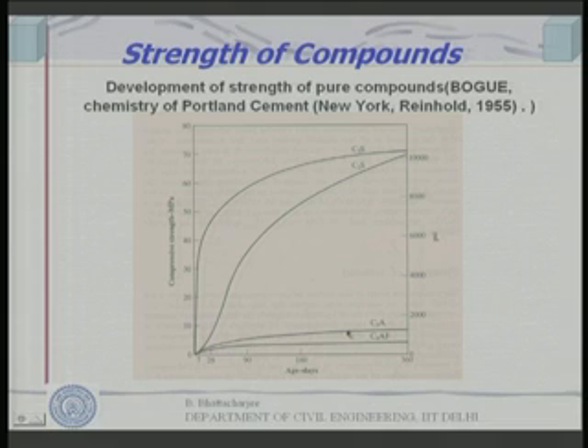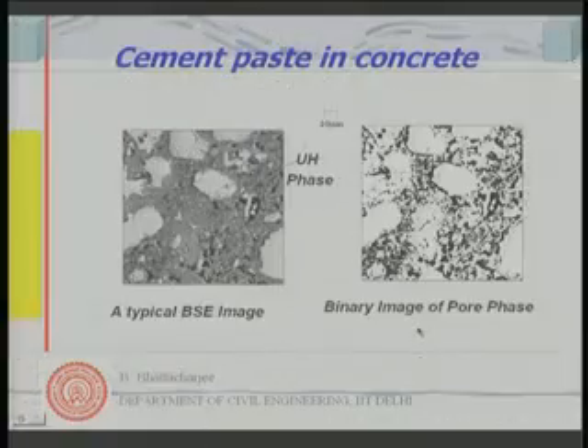C3A, on the other hand, contributes very little to the strength of the cement paste, and C4AF contributes still less, but it is a concern because it gives a lot of heat of hydration, and we will also see that it reacts with sulphate. In a hardened state, if C3A reacts with sulphate and forms ettringite, which occupies more volume, it can be a durability problem. We will discuss this later in more detail. So, we can see that C2S and C3S are the main strength-giving compounds.